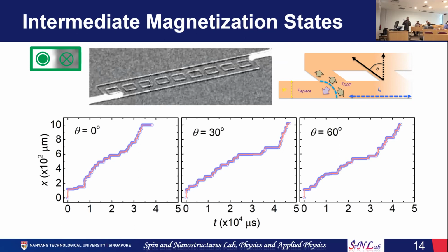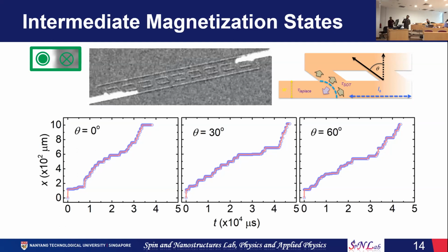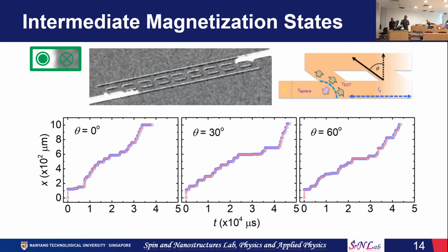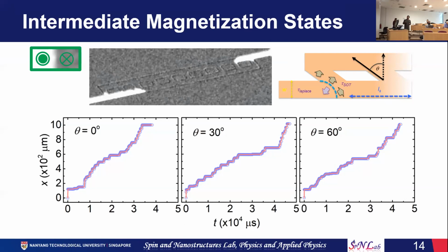Initially, a domain wall moves very fast along this segment and gets pinned at this position, and that basically gives this flat line in the variation of the domain wall motion with respect to time. So we get multiple magnetization states. In total 19 states we observe, and that is a nice result in terms of experimental verification.